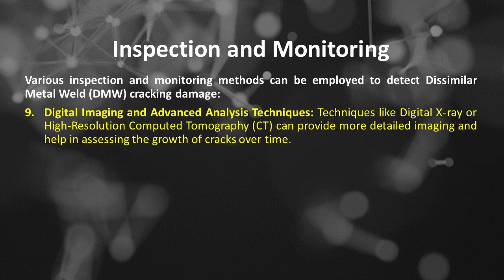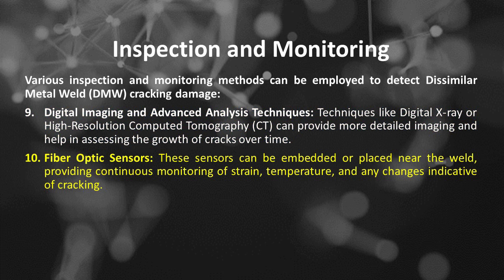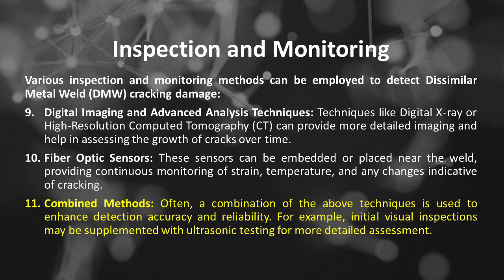Number 9 is digital imaging and advanced analysis techniques. Techniques like digital X-ray or high-resolution computed tomography, or CT, can provide more detailed imaging and help in assessing the growth of cracks over time. Number 10 is fiber optic sensors. These sensors can be embedded or placed near the weld, providing continuous monitoring of strain, temperature, and any changes indicative of cracking.